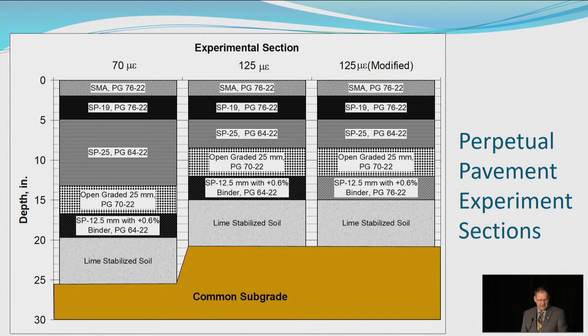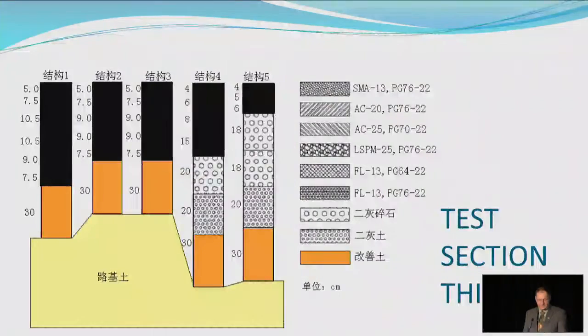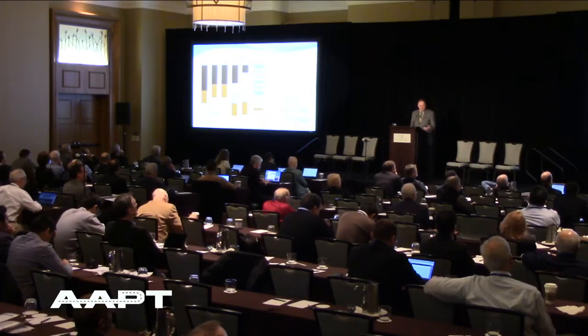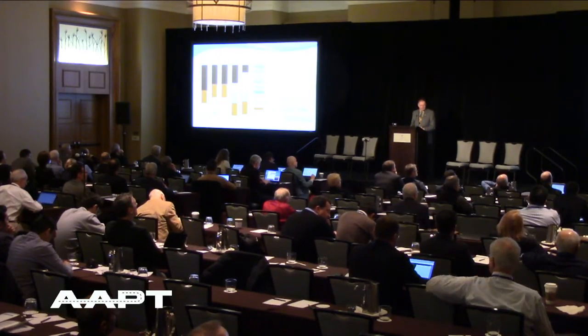One was built, you can see, to 70 microstrain as a limit. 2 of them were built to 125 microstrain. The difference with the 125 microstrain is that one had different considerations for both the base layer, which is a polymer modified asphalt binder, and the subgrade modulus. Now, putting that into the context of all 5 sections that were built, there you can see the 3 U.S.